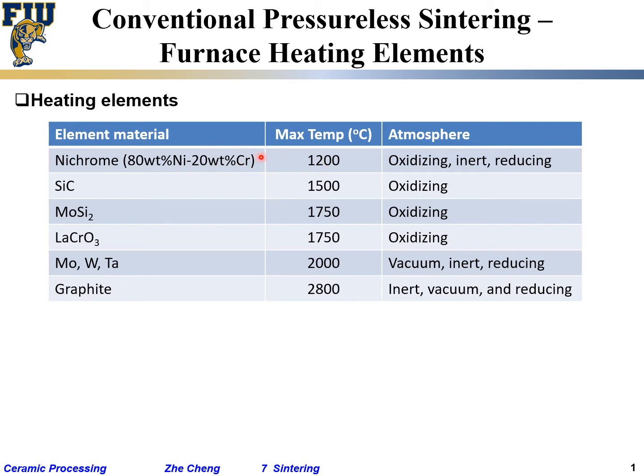These two metals do not have very high melting temperatures. Nickel melts at around 1400°C, so the highest temperature you can use is not surprisingly only around 1100–1200°C. If you want anything higher, you cannot use nichrome wire as your heating element.